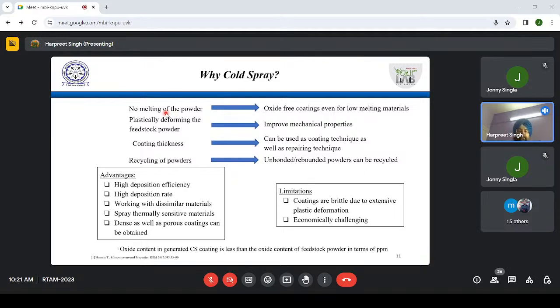So one is that no melting of the powder takes place here, right? So that means the chances of oxide formation, etc., will be reduced, especially when we have low melting temperature materials like aluminum, etc. So this gives us an added advantage, right? And plastically deforming the feedstock powder will improve the mechanical properties. It has been seen that since you are doing severe plastic deformation of the particles, their grain size also becomes refined and you get very good mechanical properties in the deposits, which is another very attractive point.